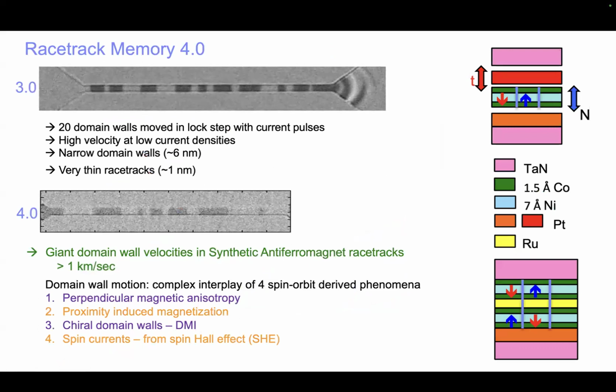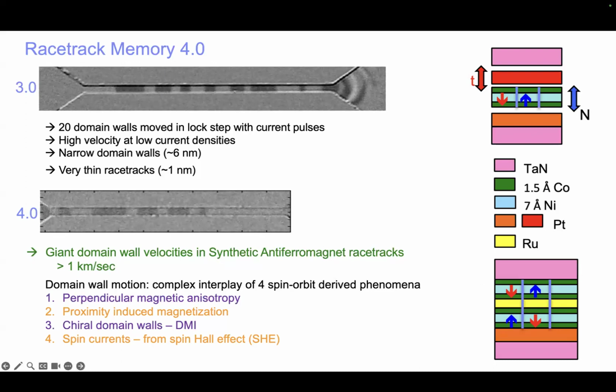So this is essentially what I've discussed. We've created a racetrack. Shown on the right-hand side, you can see a schematic representation on the top of a simple ferromagnetic racetrack. The green and blue layers can correspond to ultra-thin layers of cobalt and nickel, each layer a few angstroms thick. The orange layer would be this platinum layer, with which we generate the spin-orbit torques. And on the bottom, you can see a synthetic anti-ferromagnetic racetrack, which again consists of these atomically engineered cobalt-nickel-cobalt layers. The interfaces break symmetry and give rise to strong perpendicular magnetic anisotropy. The yellow layer is this ultra-thin layer of ruthenium that leads to this strong anti-ferromagnetic coupling. And then you have a synthetic antiferromagnet in which the domain walls under the current pulses can be moved at very high speeds exceeding 1 kilometer per second.